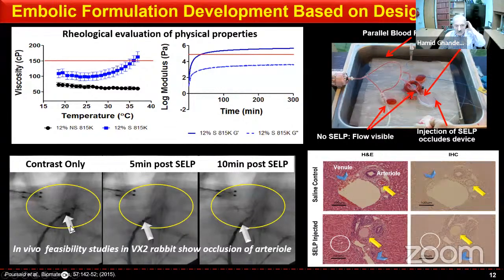And also, in these non-tumor bearing rabbits, we demonstrated that we can occlude some blood vessels here. And in fact, later when we did histology, in the saline control, the arterioles are open. In the SELP case, we can clearly see that these SELPs are forming a gel. And before we did the in vivo studies, we did some in vitro microfluidic examination of these systems where you deliver the red dye from here, and from the other side you deliver the polymer, and they form the gel. And basically that demonstrates proof of concept in vitro and in non-tumor bearing rabbits in vivo that the system works.